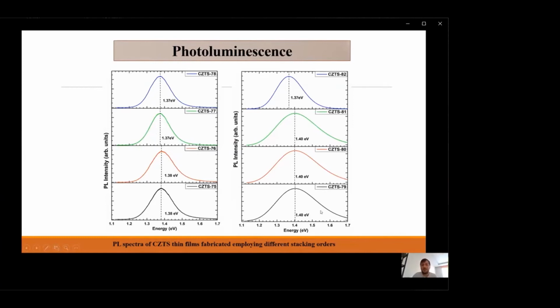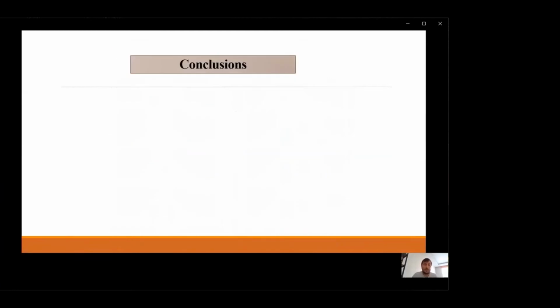Here also you can see in the B-type samples they are close to the band gap values of the CZTS samples, except for this sample. In this sample, we also observed maybe some impurities and defects in the band structure.